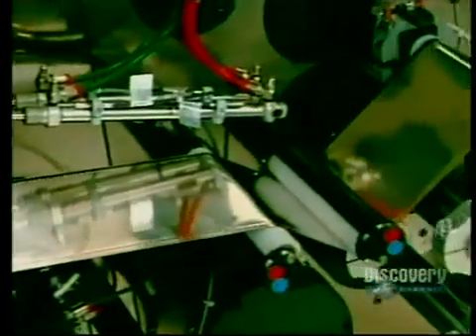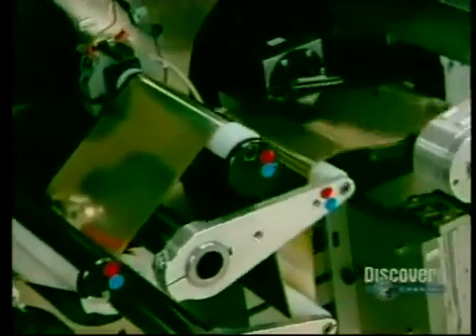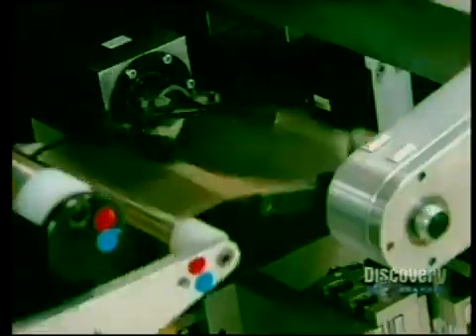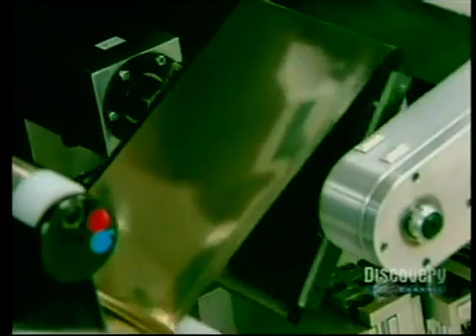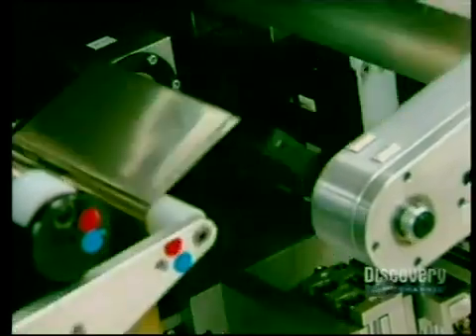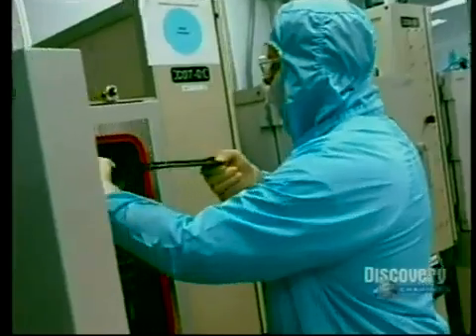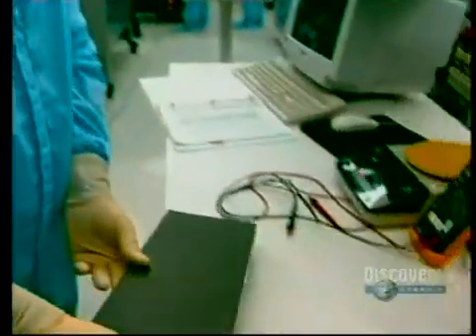To make an individual battery cell, the sheet has to be rolled up. This automated spooling machine winds up the lithium film in 26 revolutions. The wound-up sheet is then put into a vacuum oven where the various layers adhere firmly to one another.